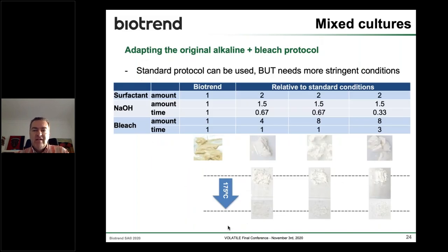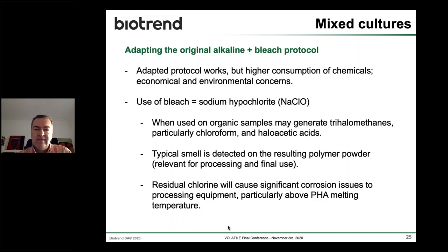So this is a bit of a challenge when you want to have a reproducible process to extract the polymer from within the cells. And the standard process that we used for pure culture production of PHA didn't work directly with the mixed cultures, and we needed to increase either the concentration of chemicals or the residence times in the reactors in order to get a decent purity in the end.